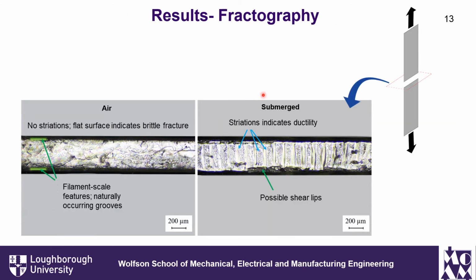After that, we also decided to look at the fracture surface of the tensile tested specimens, both air and submerged. You can see a few differences between them. First of all, there are multiple striations along the fracture plane, unlike air specimens, which show flat and smooth surface characteristics of brittle fracture. On the other hand, these striations we believe result in the ductility of the material, as we saw in the stress strain plot as well. And we can see some possible shear lips at the sites. These results are exactly similar to what we've seen for non-cyclic loading conditions. So we believe that these raised edges could be a microplasticity due to the interaction of water molecules with the polymer during its deformation.